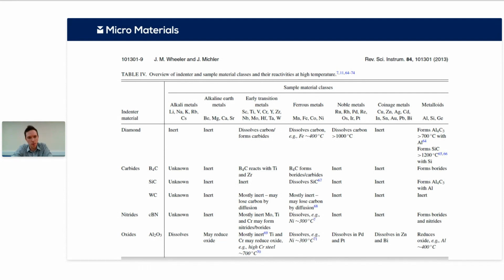I mean, tungsten carbide is the most inert with most of the sample material types. But again, that's one of the softer materials compared to the boron nitride or the diamond. So these tungsten carbide and sapphire indenters are more likely to wear because they're just not as hard as diamond and other types of material. So we have to factor that in when we're performing tests, especially on hard materials. The tip rounding will occur much quicker than it does with diamond.